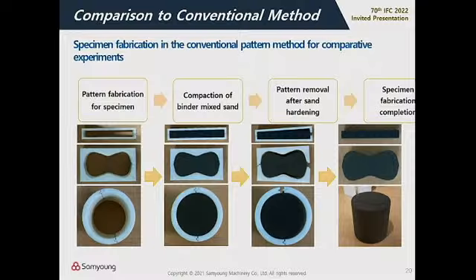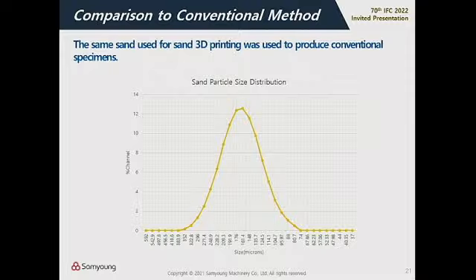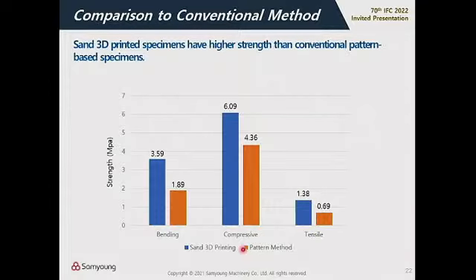Also, we did additional experiments to compare to the conventional pattern-based method. When we made specimens for the conventional method, we used the same sand used for sand 3D printing. This graph shows the sand particle size distribution. And this is the comparison result. It shows that the sand 3D printed specimens have much higher strength than the conventional pattern-based specimens in all 3 aspects: bending strength, compressive strength, and tensile strength.